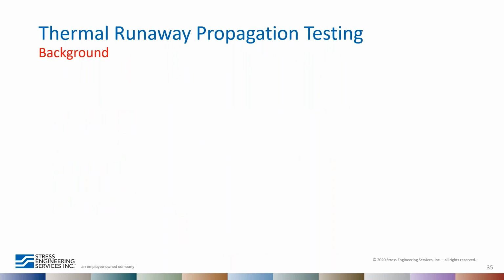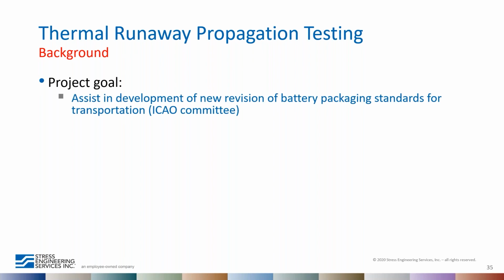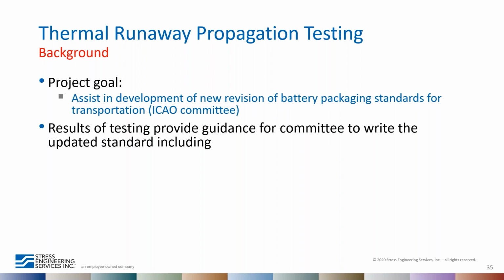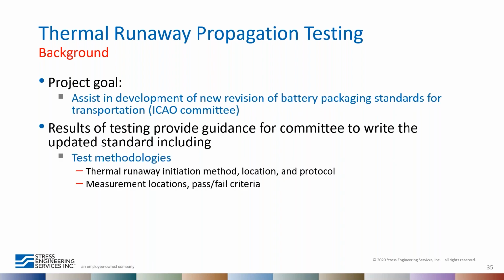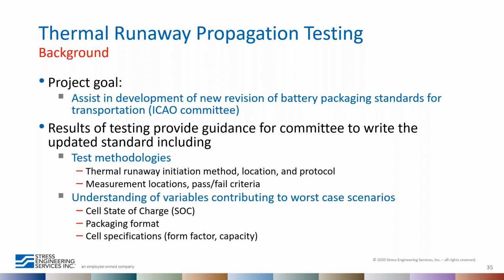So this first project is focused on assisting our client with the development of new packaging standards. The results of this test are really to understand the test methodology better and determine a suitable method for repeatable results, studying the method used to initiate thermal runaway, the location of the initiation and the protocol, and how it influences the final result. And then study different measurement locations and different pass-fail criteria. Some of the other experimental variables that were studied were the state of charge, the packaging format, and the form factor and capacity of the cells.